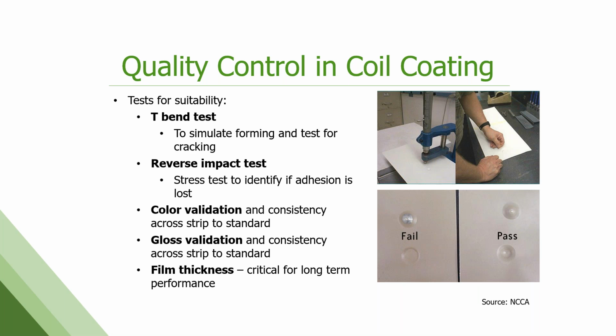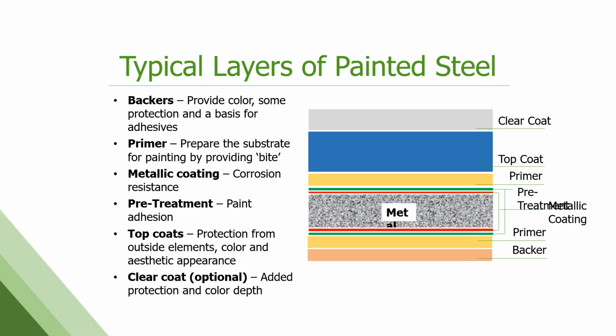We check color rigorously, which is very important, especially in the design world. That color needs to be consistent throughout the whole coil, needs to be consistent across the width of the strip, and color needs to be consistent from run to run and batch to batch. We check gloss, we check film thickness, which is very critical for not only appearance, but also the long-term performance and warranties involved, which we'll get into later in the presentation. If you want to see any of those quality control tests done for real, I think there's videos on the Coil Coating Association website as well that you can check out, and you can see those tests actually being performed and what it takes.